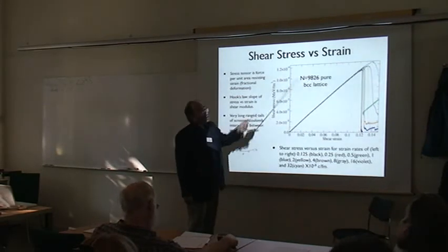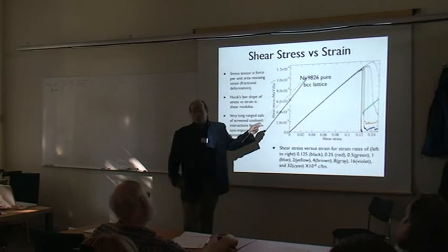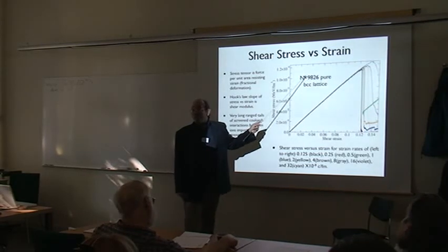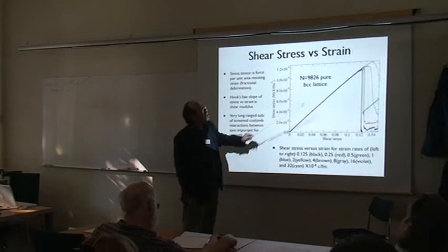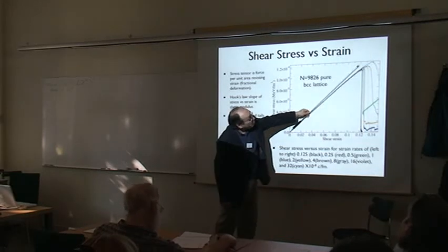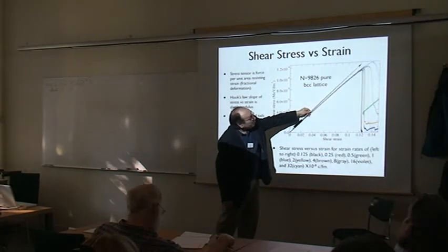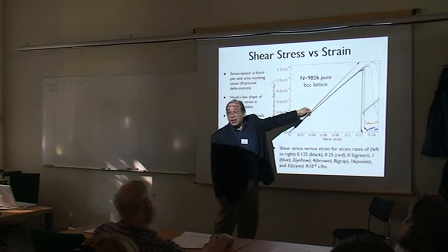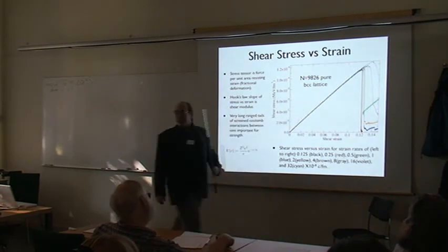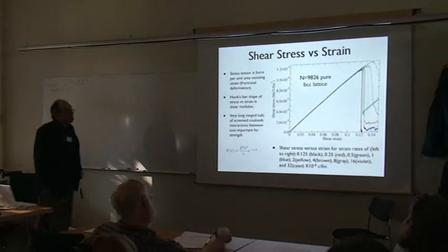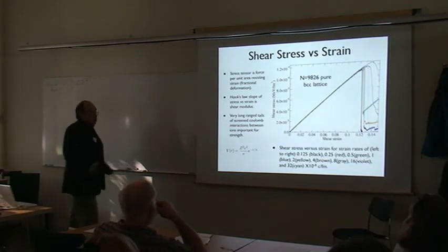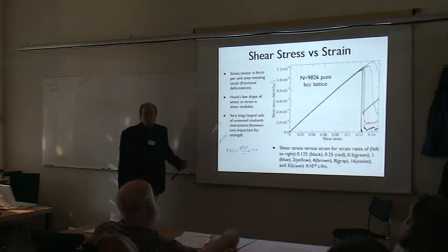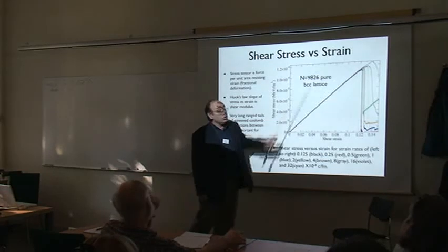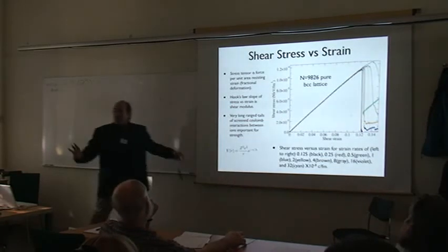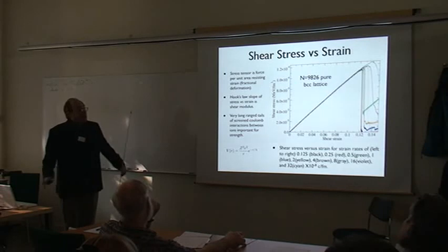This is a very small system, and I used such a small system because there are some very slow strain rates, so they ran it for a really long time. Actually, most of that curvature is a finite size effect—if I used a bigger system, it's actually straight. I mean, it's a remarkable result. I didn't expect it—that the system is basically linear, and then fails catastrophically.